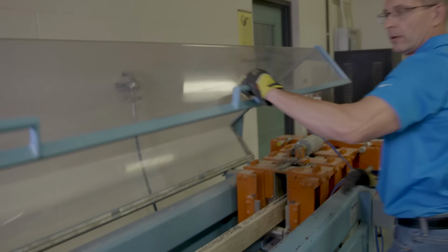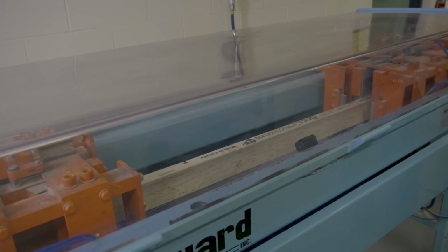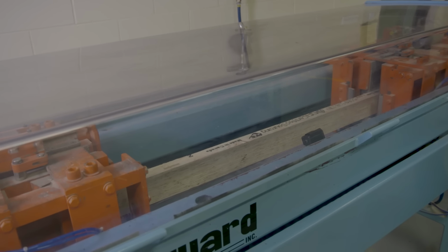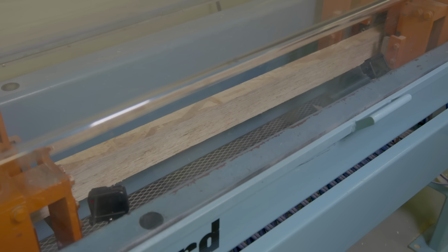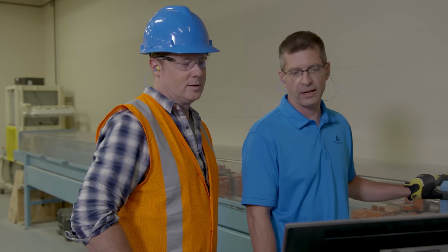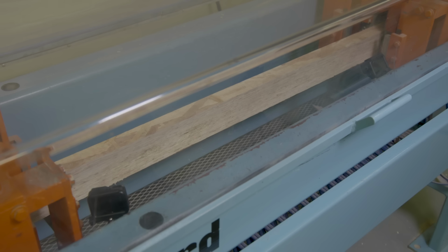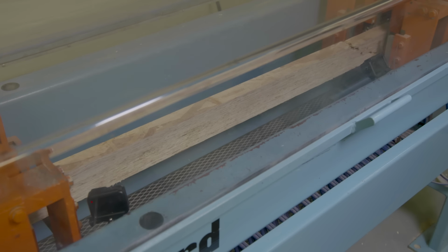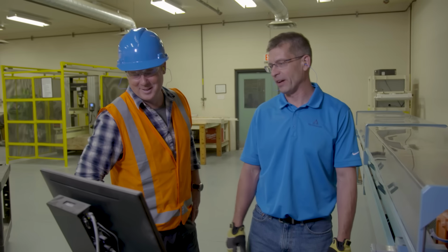Okay, Kevin, what we're going to do here is determine the tensile strength of this product. We'll turn the machine on and it'll basically just rip it in half. So what am I looking at here? What are the different metrics? What this is telling us is the amount of load, or pounds force, it has on that tension. Climbing fast. Climbing fast, and it should break at approximately over 30,000 pounds to bring it to failure. 30,000. That's it. That's unbelievable. So that broke at over 35,000 pounds.